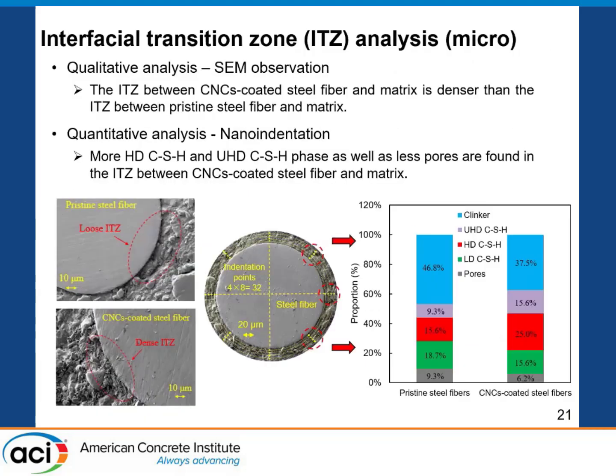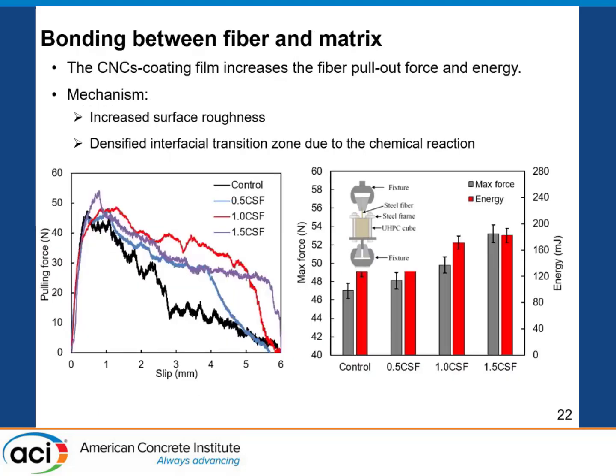So here is what we observed. This is the pristine steel fiber, and this is the CNC-coated steel fiber. If you look at the ITZ of the CNC-coated steel fibers, it looks denser. So we did a quantification using nanoindentation, and we observed that the ITZ around the CNC-coated steel fibers has more high density CSH and ultra high density CSH. It also has much fewer pores in this area, in the ITZ. Because of the improvement of the physical interlock and the promotion of the chemical reaction, we have a significant improvement in the bonding between the fibers and the matrix.